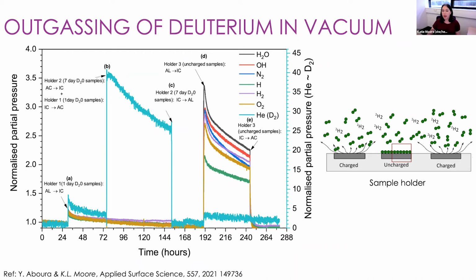And we found we could never measure the natural isotope ratio of deuterium, 0.015%, from an uncharged sample, because we were getting deuterium depositing on all surfaces inside the NanoSIMS. So this has implications for measuring uncharged samples, but it also means that any part of our sample that does not contain deuterium from our charging, we would never be able to measure the natural isotope ratio. So it has an effect on our detection limits.